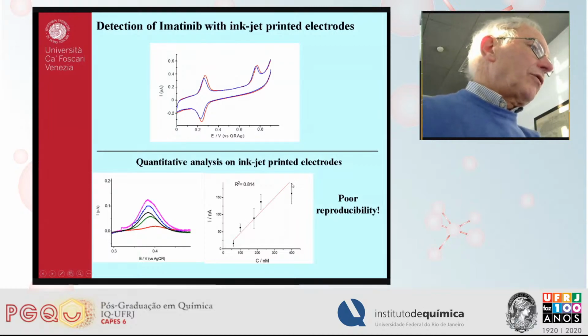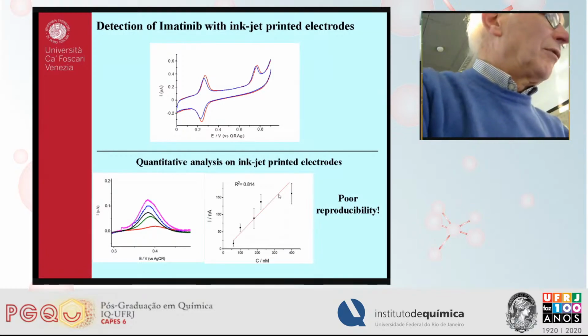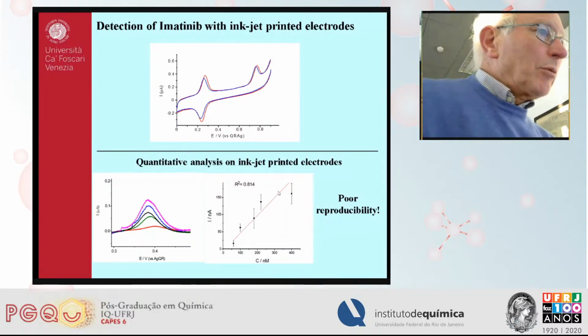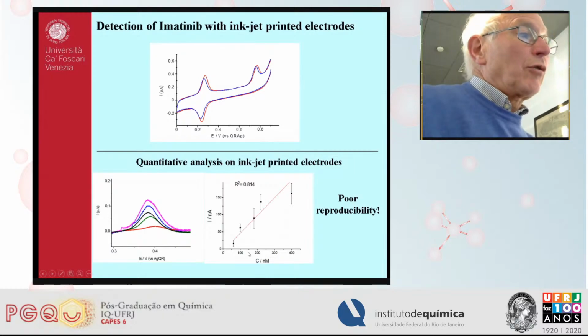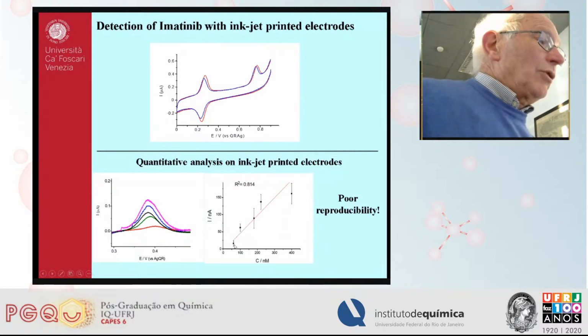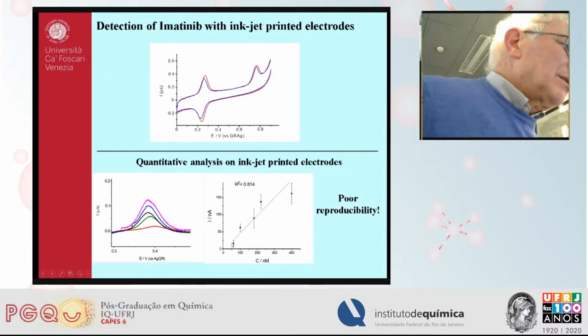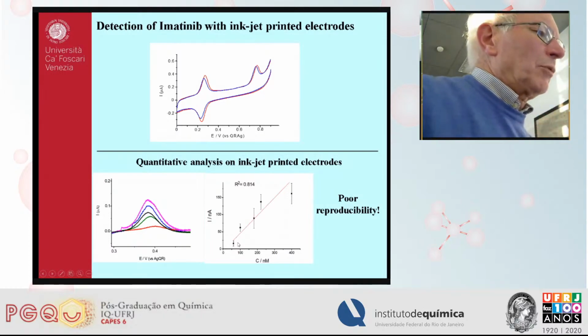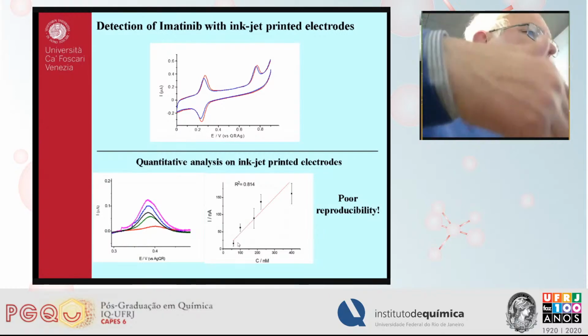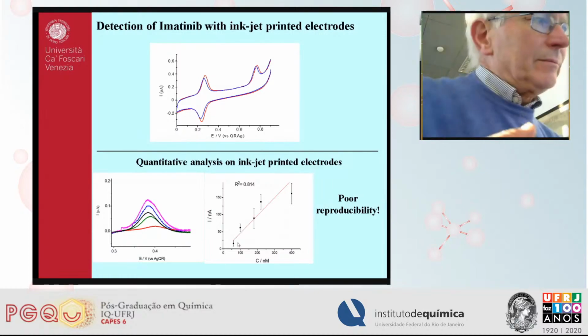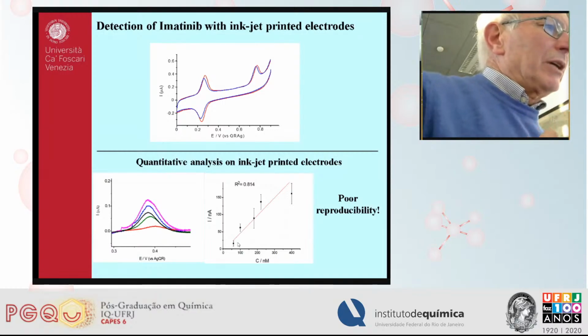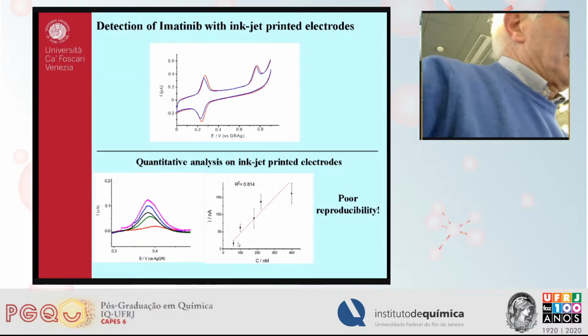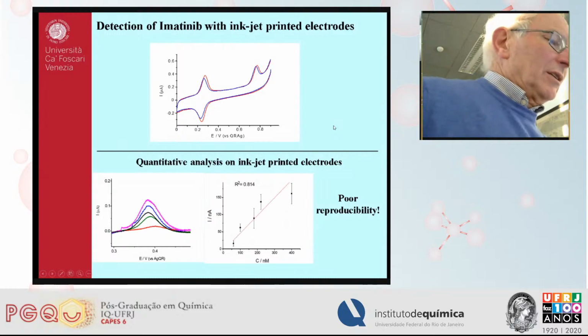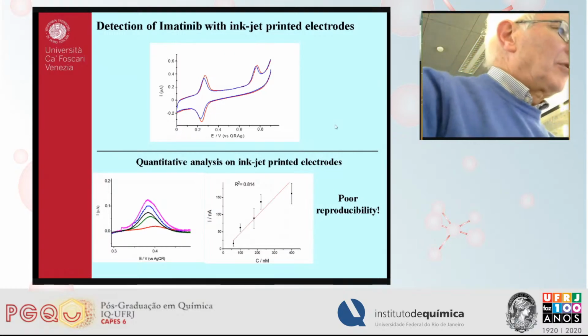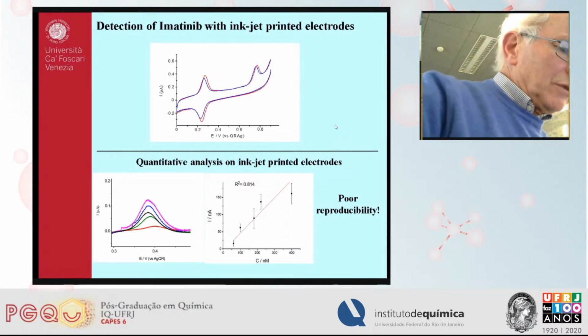As you can see, although there is a straight line which can be drawn from these points, the reproducibility is very low. Probably this kind of electrode can be used just for one measurement, and then you have to change the electrode to make the second and so on for the other measurements. But we actually did this kind of measurement, but probably the surface area of the working electrode was not so reproducible, and also in this case we didn't get good reproducibility. Anyway, by trying other inks, probably one can get some stable system also in some kinds of organic solvent. But by now, we didn't succeed to achieve these results.